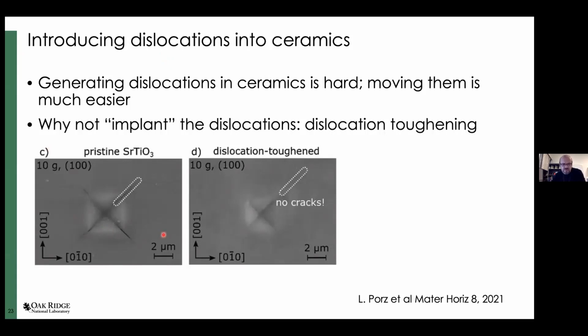And what is shown here, I believe this dislocation-toughened SrTiO3 was produced by flash sintering procedure. Another procedure that can plastically deform ceramics and introduce dislocations is aerosol deposition, where you accelerate particles to very high velocity, and due to impact, you generate a lot of deformation and dislocations. But the results are quite clear. You can see the cracking here, and after dislocation toughening, the same Berkovich indentation produces no cracks. So that could be one of the potential routes to battle that brittleness in crystalline ionic conductors.